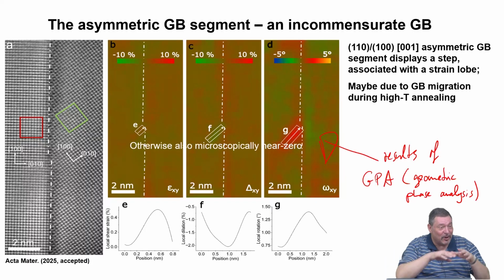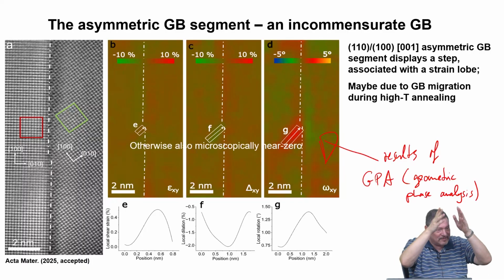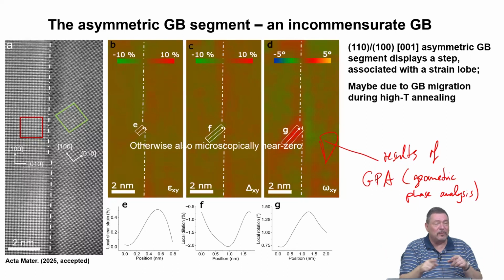In reality, we always see a spread of intensity. It's not delta distributed, but it has some distribution in space. So there is intensity diffracted into different k vectors of the Fourier space. And that means strain is in the lattice. This is the way geometric phase analysis mathematically analyzes strain with atomic resolution from high-resolution images.